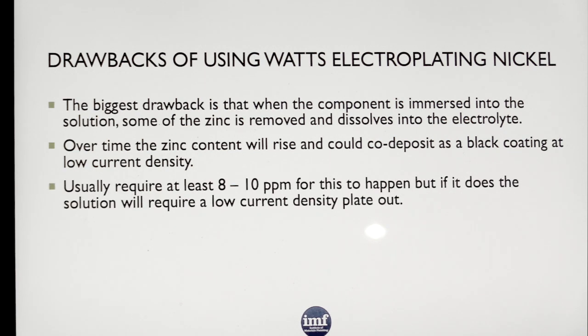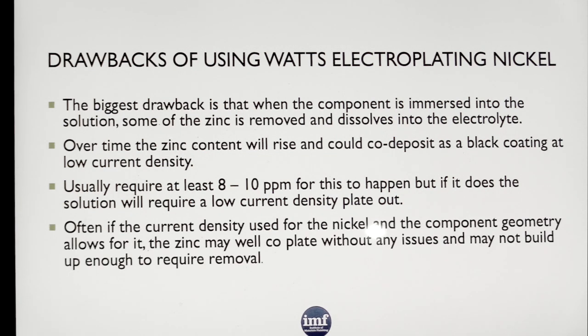You're usually looking for somewhere between 8 and 10 parts per million for this to happen. If it does start to happen, you then have to treat it, get rid of the zinc out of the bath with low current density. But often, there's a company not too far from here who plates 100% aluminium in a nickel bath. They never had to do a plating out because of the design of the jobs that they do. It's plating out all the time, but it's in such low concentrations you never see it, so they don't have a problem with it.